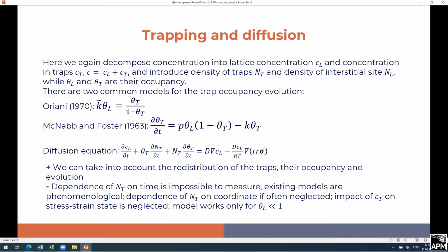And also the Foster equation was proposed only for lattice occupations which are relatively small, pretending that most of the diffusion goes into the traps, which is also quite a controversial question, because if we have a boundary layer with a high concentration of hydrogen, the interstitial occupancy would be relatively big, and this model would not work.